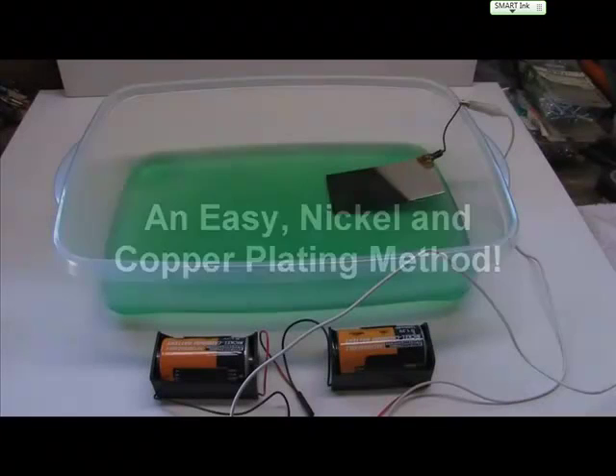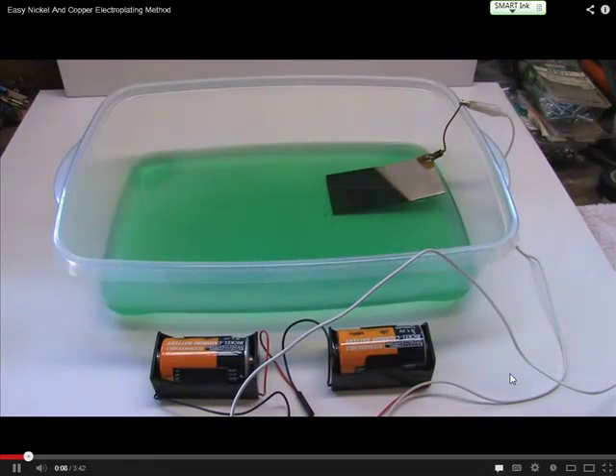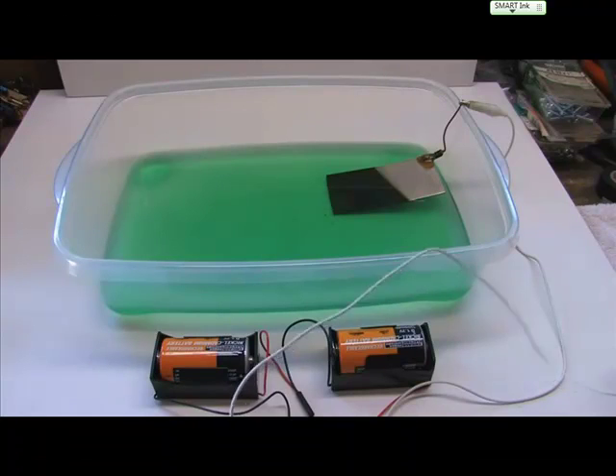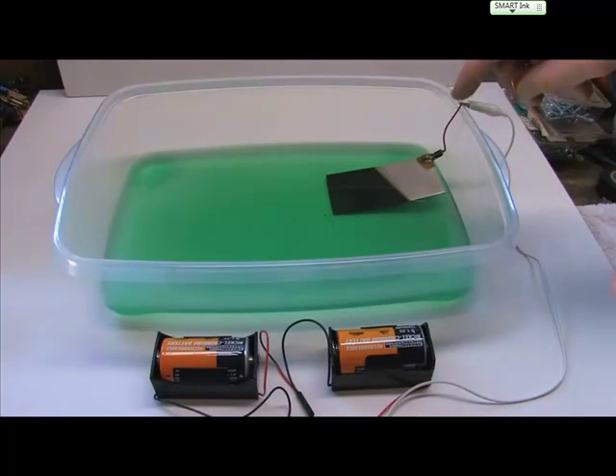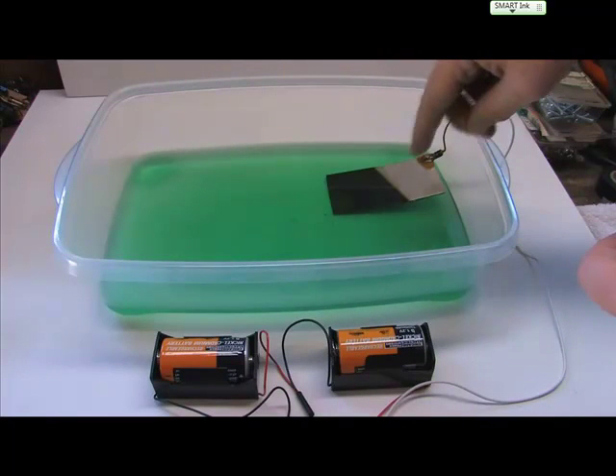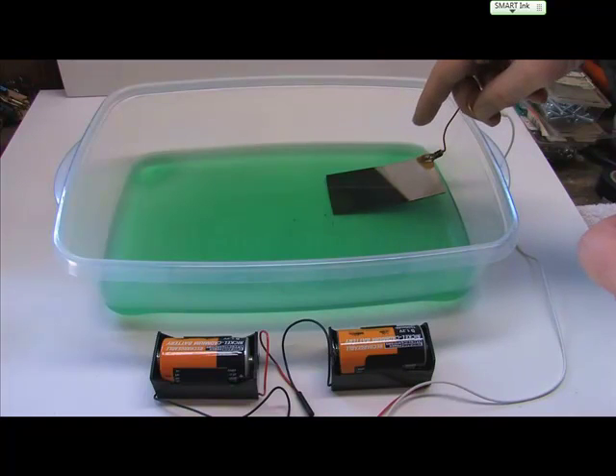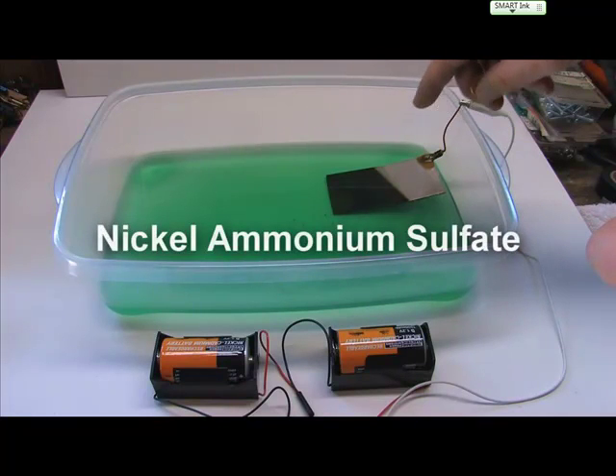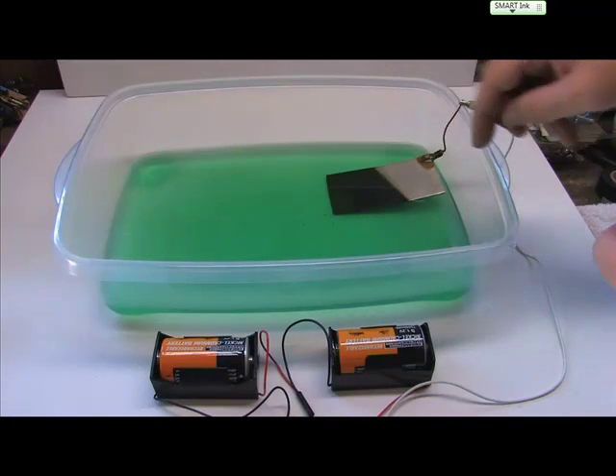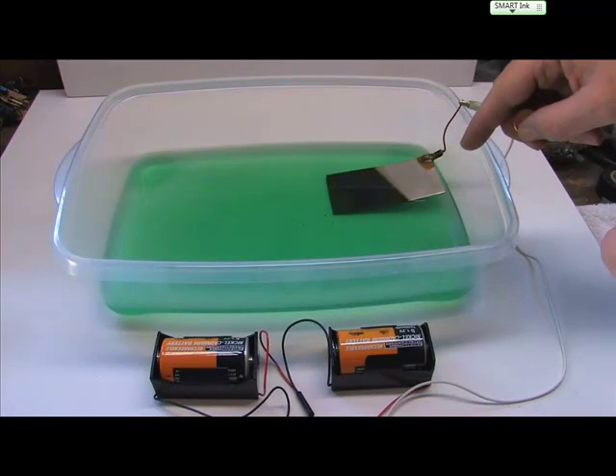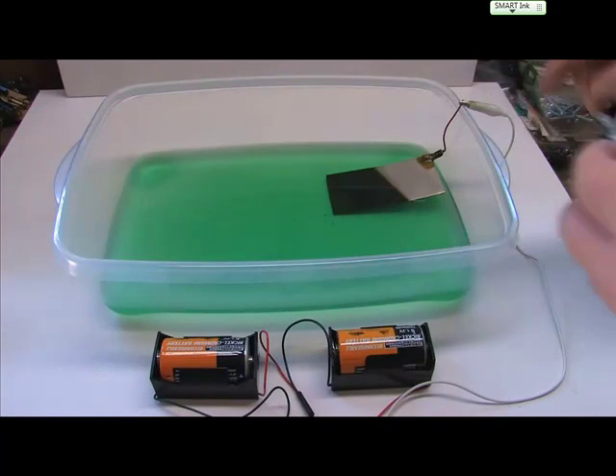You can do this at home. It's a super simple way to do nickel electroplating. Before I electroplate my item, I like to make a little nickel bath here. The water is very warm. It actually started out as boiling water. Inside of here, I have a solution which is just pure tap water with nickel ammonium sulfate, and I mixed 1 quart of tap water to 3 ounces of nickel ammonium sulfate.